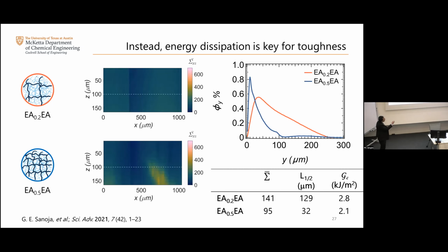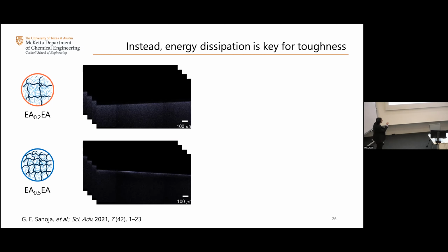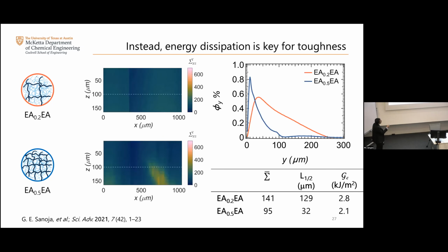But here on the upper right, what you have is the profiles. Effectively, if I integrate my damage along this direction and along this direction, I can have a profile of how much damage I have away from the crack surface. And what that enables us to do is get a characteristic length scale of over what distance my damage is concentrated, and effectively how much damage I have. So this is similar to what I did in the fatigue case, but I think this is more illustrative to show the potential of the methodology in terms of three-dimensional space.